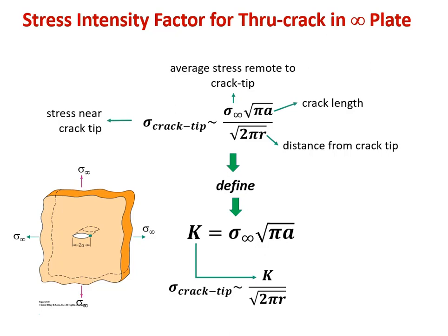So now we're kind of taking out the part that had to do with where we were relative to the crack and just talking about what load did we apply and how big the crack was to start with. So we're defining that constant K as your applied stress, applied load per unit area, times the square root of pi times the square root of your pre-existing crack length.